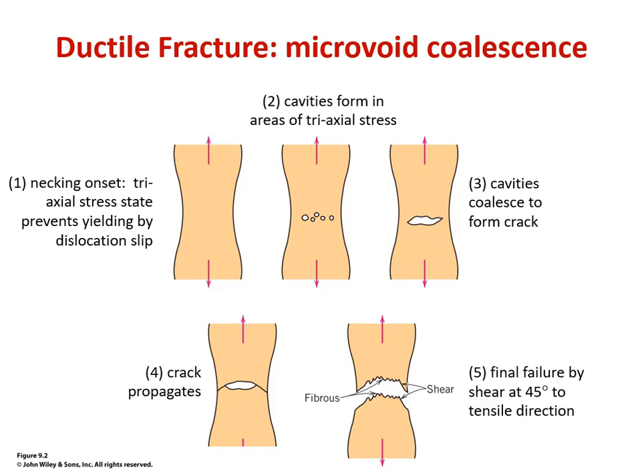If you go to the next schematic over in the middle on the top row, you can see that as we have continued to increase the applied stress in that necked area, we've now started to form little cavities. These are basically small defects in the material that were pre-existing, right along the same scale as the grain boundaries. They start to grow. As we continue to apply more and more stress, these will coalesce. They will join together and eventually form a macroscopic crack. Again, as we continue to apply more stress, that will propagate and eventually reach the point where we overload ductilely, and the final failure is shear failure, and we'll form what are called shear lips on the outer circumference of the material. And those are, of course, at 45 degrees to the uniaxial tensile direction.